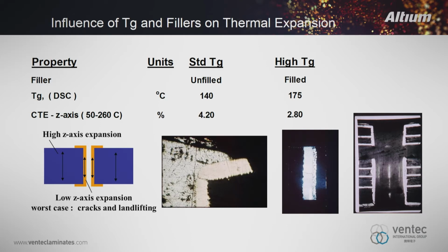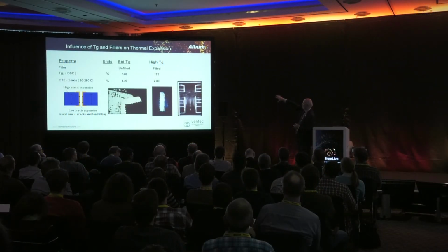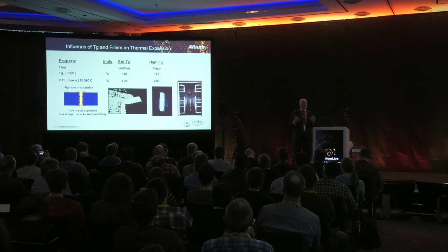So the CTE is a crucial property. It's especially difficult when you come to thick materials because the absolute magnitude is much higher. Thin materials, no problem, but thick materials are a huge issue. So we've come towards this kind of phenolic curing system for the thermal endurance. We've also come towards using a filler to get this CTE value down as well. So people would talk about filled phenolic epoxy resins. That's what we're talking about here. So filled with a filler of some kind, and then using a phenolic curing system just to get that extra reliability for the lead-free soldering.